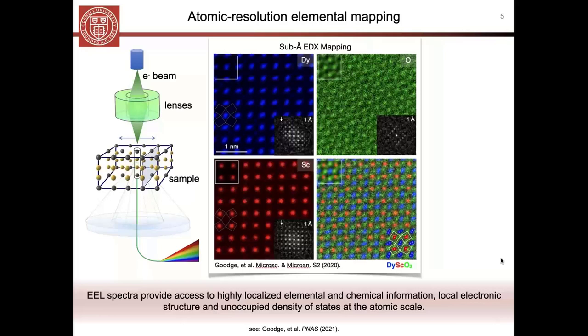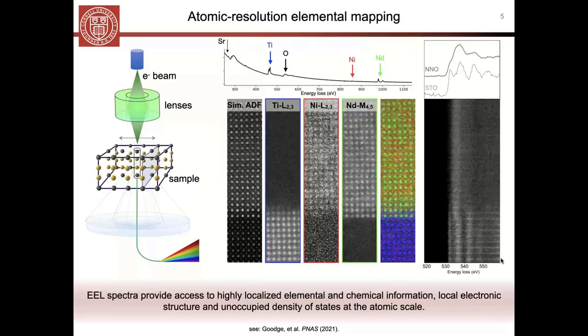But what EELS can do that EDX can't is access the chemical information of the atoms that we're looking at. Here you can see plotted a spectrum profile across the same interface on the left, and this is the oxygen K edge. The oxygen edge in these materials holds a lot of very rich chemical and electronic information about the actual states that are present in these materials.